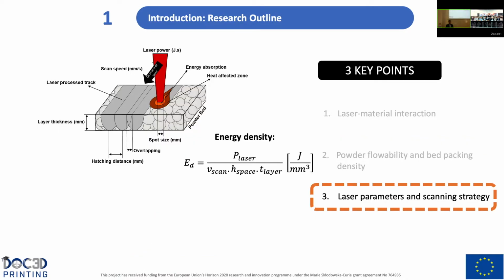And finally, of course, the laser parameters and scanning strategy. The 2 most important laser parameters are the laser power and scanning speed. Why? Because they determine the energy density that we are applying to the powder. Next, the layer thickness, which is the depth of each layer during the process. And here we need to assure that we have a short distance so that we interact with the whole depth with the laser. And finally, the hatching distance, which is the distance between 2 adjacent laser beam tracks.